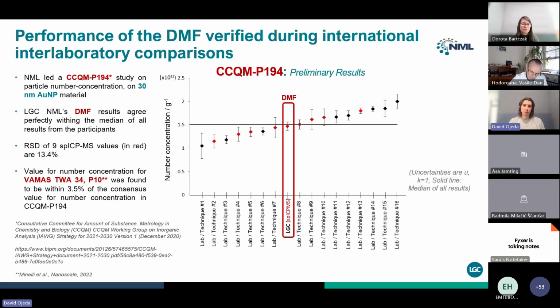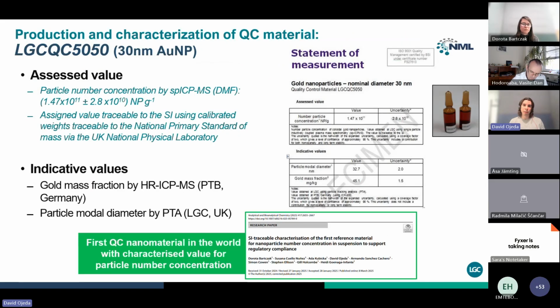In parallel to these studies, this material, the 30 nanometer gold particles, was also used for the production and characterization of the quality control material named LGCQC 5050. And we obtained an assessed value of particle number concentration with the DMF that was SI traceable. On the right-hand side, we can see the certificate for this material. The most important thing to state is that this was the first quality control nanomaterial in the world with a characterized value for particle number concentration.